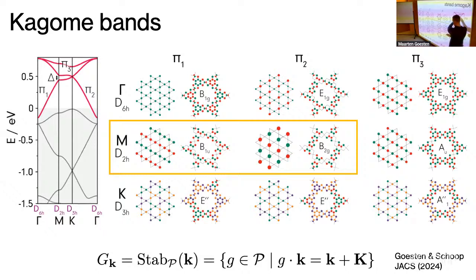So if you actually zoom out, you will find this pattern replicated 6, 7, 8 times when you go down from the Fermi level, because we have many atoms. So for every orbital we have a band, right? Yeah, because that band is touching the Fermi level, so I was wondering what that band is. Yeah, that's true. If you would synthesize this 2D MOF, and a lot of calculations have been done on that, then you would get this band structure, which is inherently metallic.